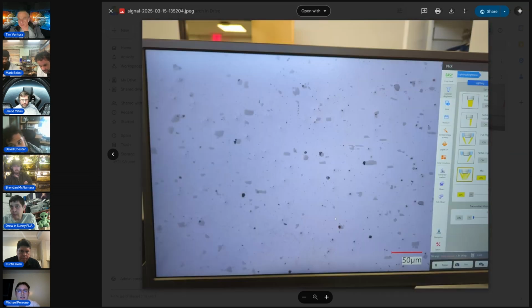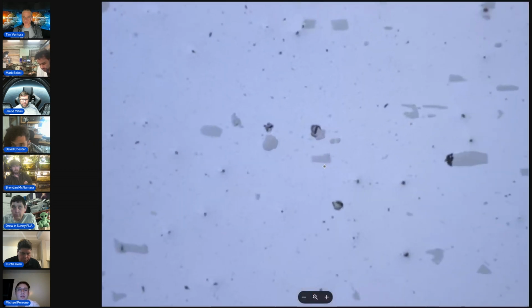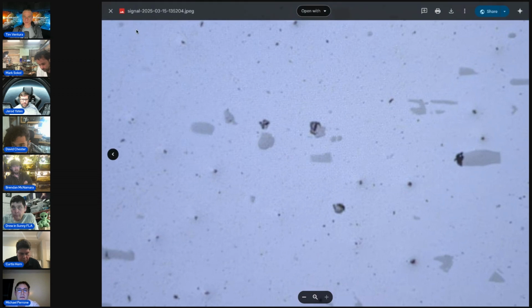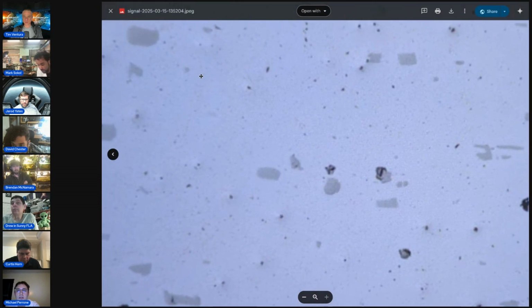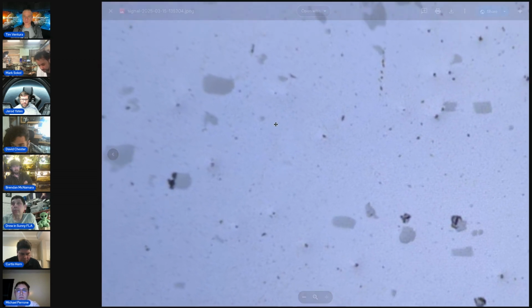Yeah, and this is the optical microscopy, and you can see that there's two phases. So it's probably like an aluminum silicide phase dispersed in an aluminum phase, and then the magnesium and manganese would be at such a low percentage that they're not forming any third phases or anything. They're just diffused throughout the other phases. The black stuff is probably holes.